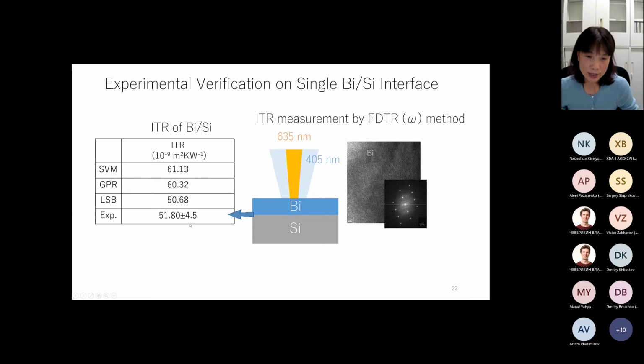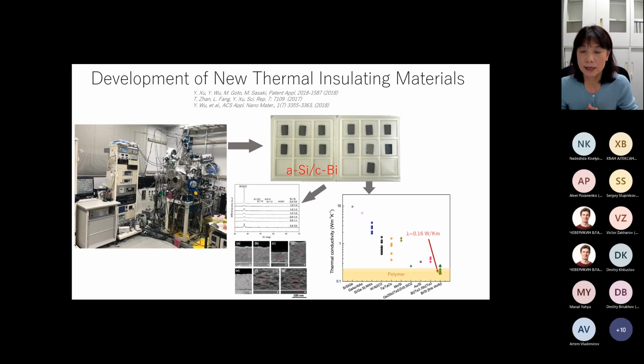And here is our experimental result in comparison with the machine learning prediction. The SVM and the GPR give a very similar prediction. And unfortunately, our result supports the LSB model. So that means that statistical accuracy alone may not be enough to judge the reliability of a machine learning model. And then next, we try to make a nanostructured material with bismuth and silicon.